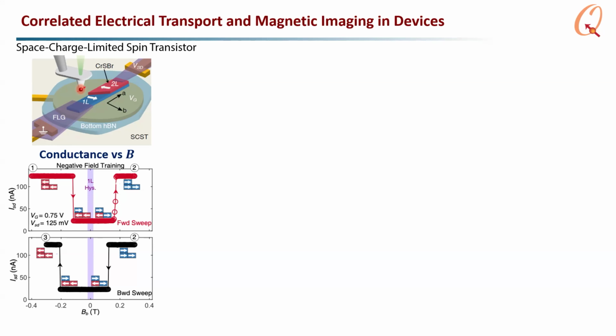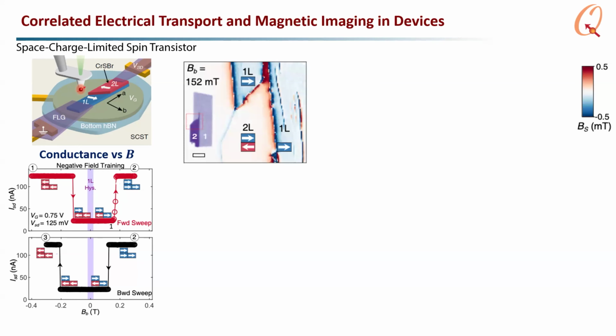So in this case, we can measure the device conductance as a function of field, and then you see that the current jumps whenever the bilayer switches to a ferromagnetic state. Whenever the layers are aligned, then you have hopping allowed between the layers, so the conductance goes up. But sometimes you see a gradual antiferromagnetic to ferromagnetic transition, and sometimes you see a sharp one. So gradual meaning I see intermediate levels of the conductance.